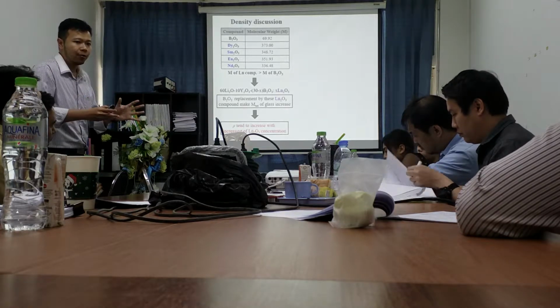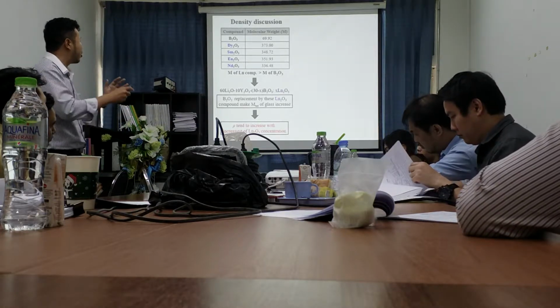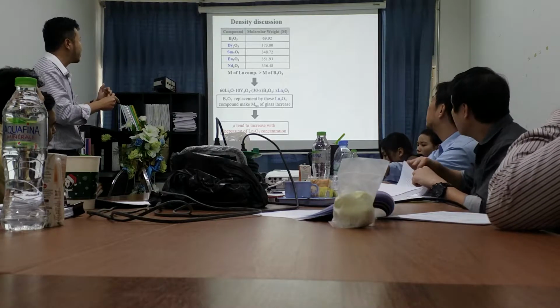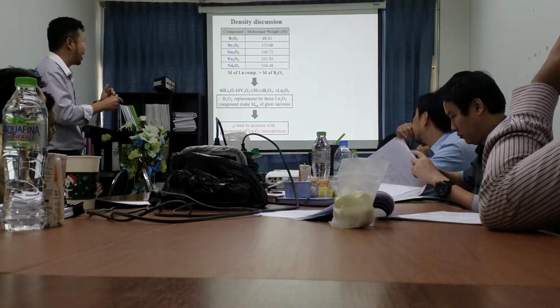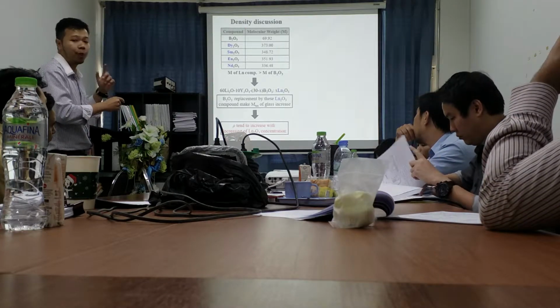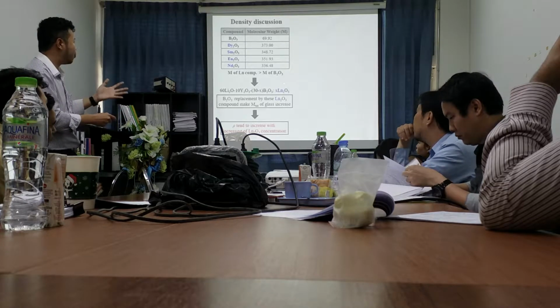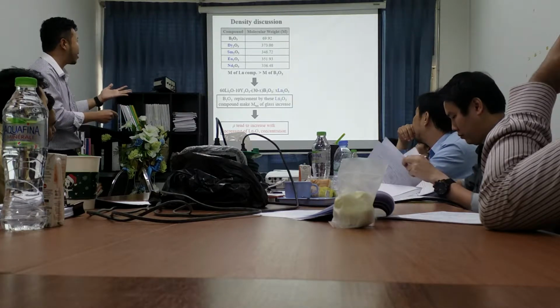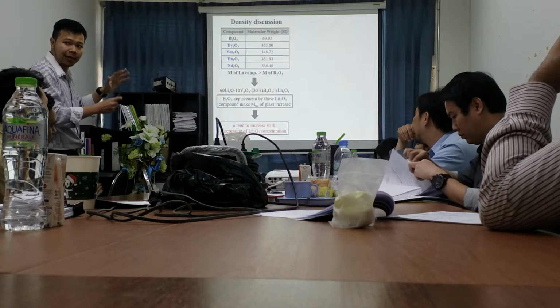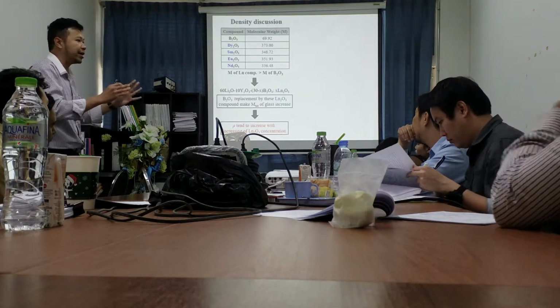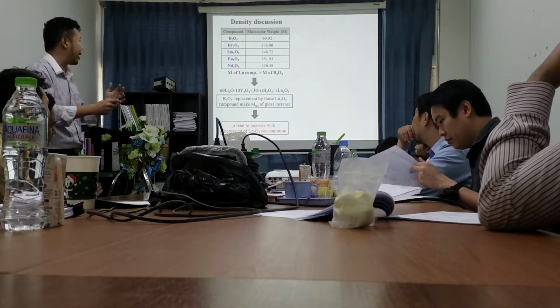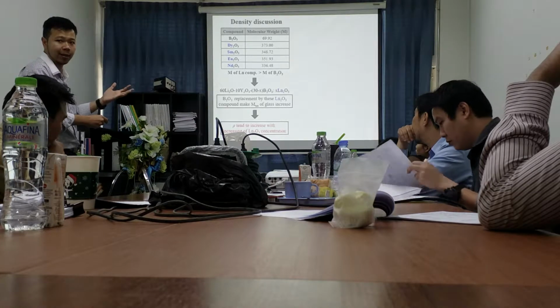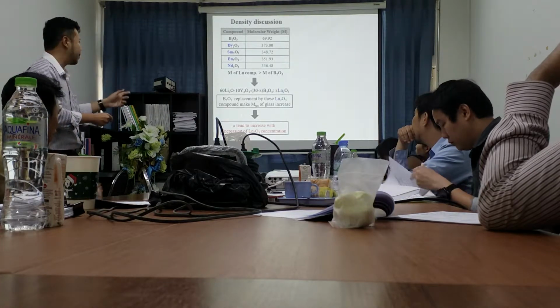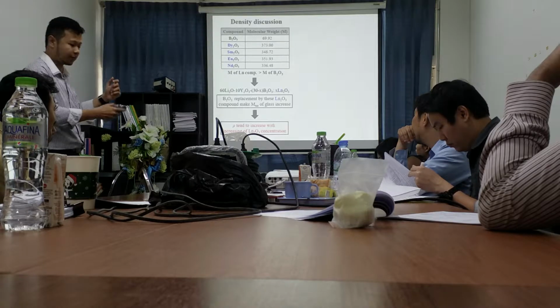About the density, we can say that because dysprosium, samarium, europium, and neodymium oxides are heavier than borate, when we dope more of these lanthanide ions, the borate is reduced. That means we replace it with heavier elements, and it makes the total molecular weight of the glass higher, and this makes the glass more dense.